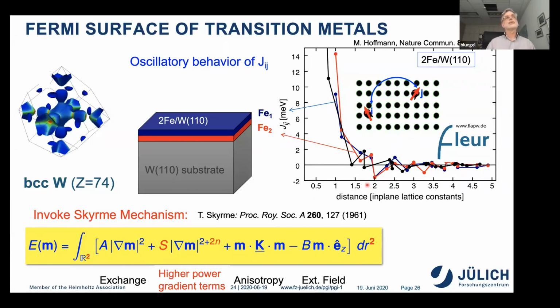So basically, what you do, you have to go to higher orders. And this brings you to a micromagnetic equation, which is basically more similar or equivalent to the actual Skyrme mechanism. So usually our skyrmion is stabilized by a gradient term, by a chiral symmetry breaking term, whereas the true Skyrme mechanism was a higher power gradient. And with this frustration, you come closer to these higher power gradients.